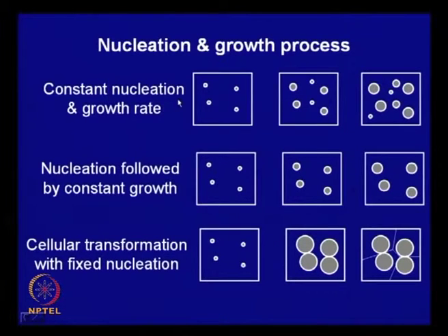So, you have nucleation going on, and you have growth of stable nuclei. Two processes take place parallelly, whereas we can also think about a process like this. Say we assume that there are only certain specified sites where nucleation can take place, and only after all these sites have some precipitate or some transformation product, will the subsequent transformation take place.